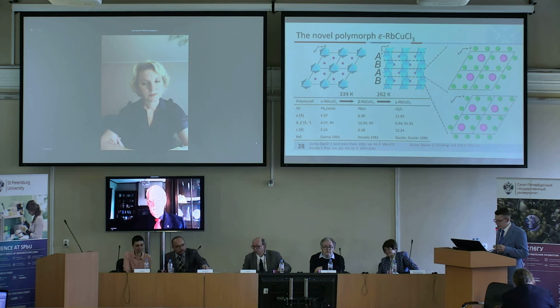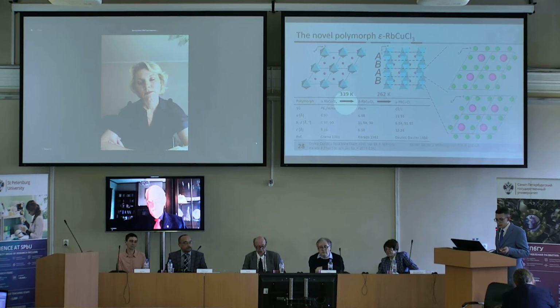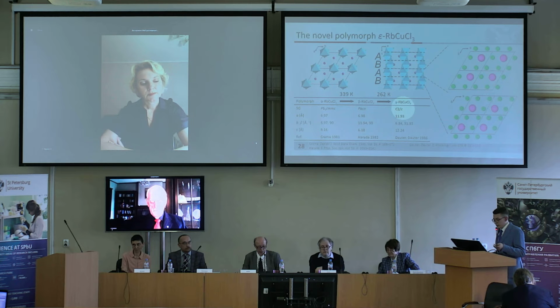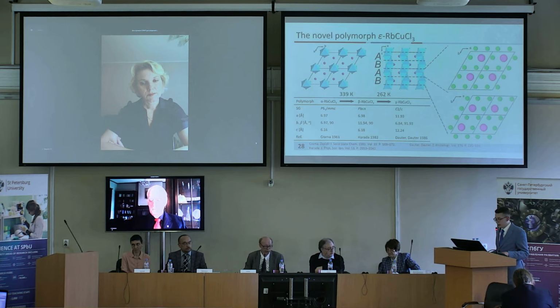That is an excellent demonstration of the structural transition of the second order under the influence of temperature. The alpha phase exists at temperatures above 339 degrees Kelvin. When the temperature decreases, there is a transition to the beta modification, with a decrease in symmetry to rhombic. And at 262 degrees, there's a transition to the gamma modification with monoclinic symmetry.